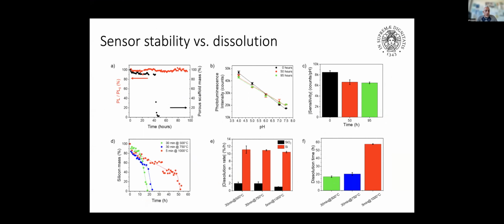Once the scaffold has been degraded, the nice thing is that, as you see here, the polyelectrolyte multilayer still works for at least 50 more hours and then degrades. So this is interesting because it doesn't mean that the porous silicon is just a scaffold to increase the amount of polyelectrolyte you can bring, but the polyelectrolyte multilayer works by itself.